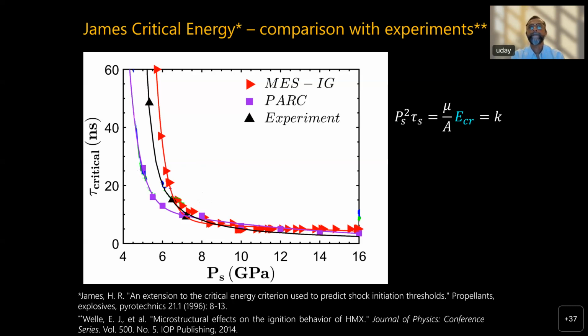Now, having said that, we've done recent work that shows that for small void sizes, by which I mean about a 1 micron diameter, void-void interactions may not be a terribly strong effect. For larger void diameters, we find void-void interactions a very strong effect. So I think in this instance, because the void sizes in class 5 center around about 0.5 micron, I don't know if the void-void interactions will play a major role in the discrepancies that exist in the predictions for this particular case. But I think PARC actually should take into account void-void interactions.